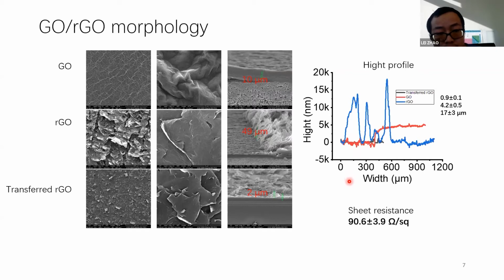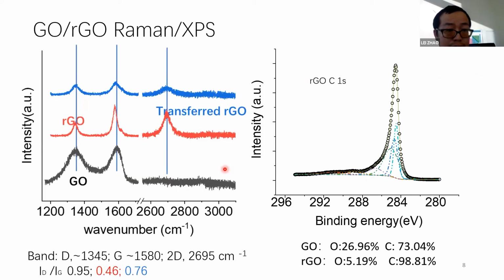Then we tested the materials with a 4-probe system and got a sheet resistance of around 90 ohm per square, which means it has good conductivity. The reduction was also confirmed by Raman. As you can see here, the graphene oxide film shows the typical D band and G band of graphene-based materials. After applying the laser, the G band increased dramatically, and the 2D band starts showing up. With the XPS analysis, we found that after applying the laser, the oxygen component was reduced a lot. This proves the graphene oxide was successfully reduced.